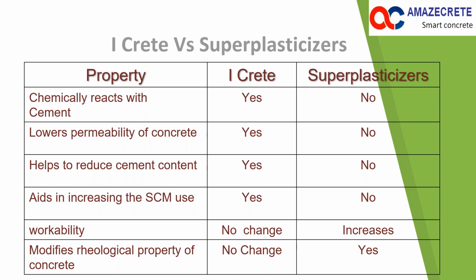Whereas iCrete chemically reacts with the concrete, lowers the permeability of concrete, and reduces the cement content. iCrete increases the SCM usage, and then most importantly, there is no effect on the workability or rheology.